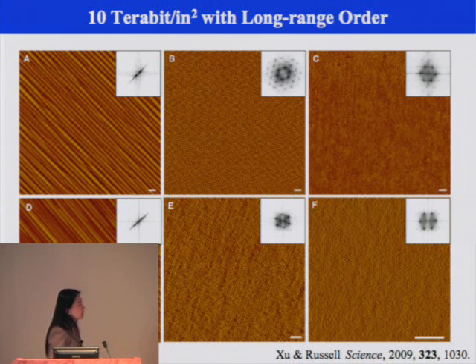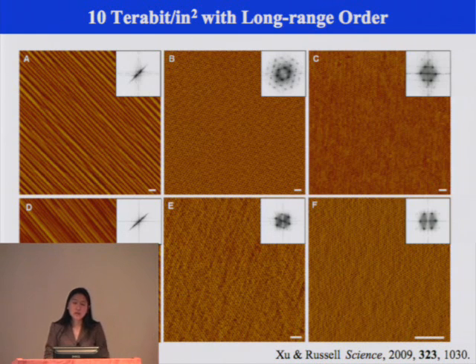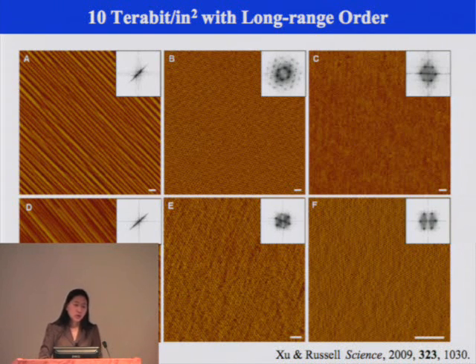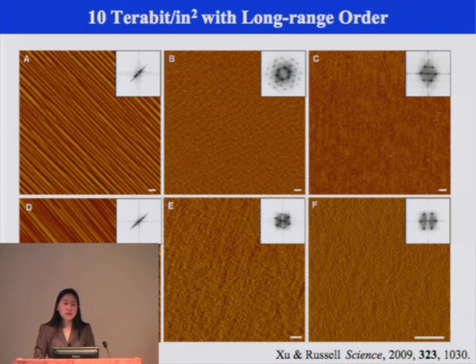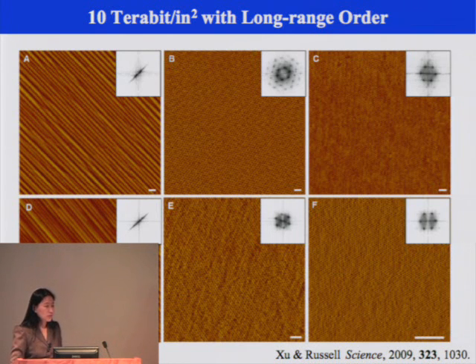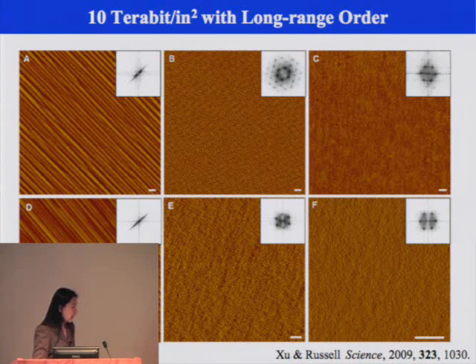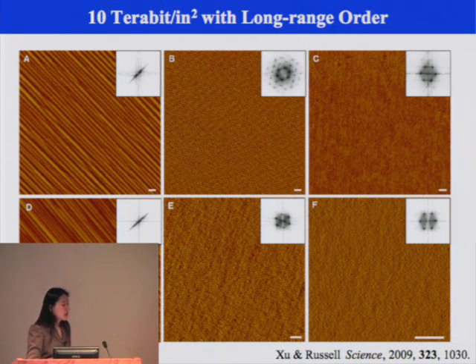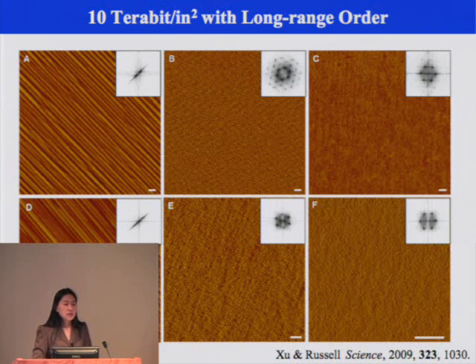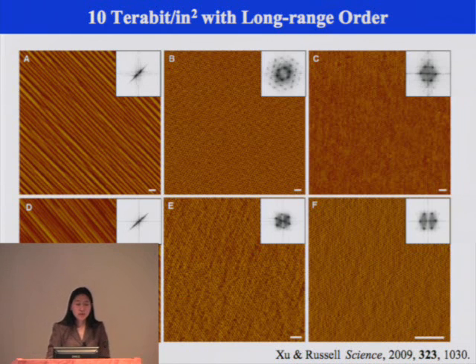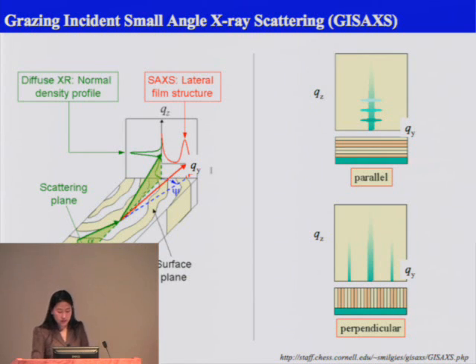The take-home message is that for all the samples we looked at, you can see they have hexagonal packing with really good long-range order. And if you do image analysis, the translational order is also fairly good. What I want to bring to your attention is that in this case the interdistance between the cylindrical microdomains is about 7 nanometers, and that is fairly small.